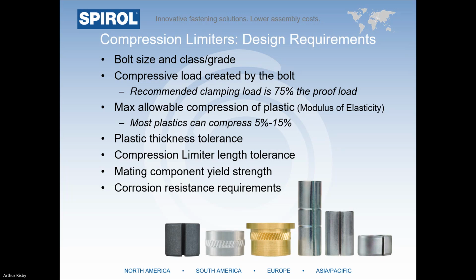The plastic thickness and compression limiter length tolerances are also very important. Ideally, the maximum compression limiter length should be equal to or below the minimum thickness of the plastic without exceeding max compression. See how this is all intertwined with each other? The yield strength of the mating component is also important, as you don't want to indent the material of the mating part, creating witness marks, when the bolt is torqued to the recommended tightening torque. And finally, we want to understand the environment in which the compression limiter will be exposed, as we want to understand both the environmental and the galvanic corrosion requirements.